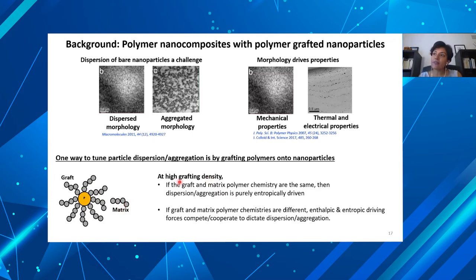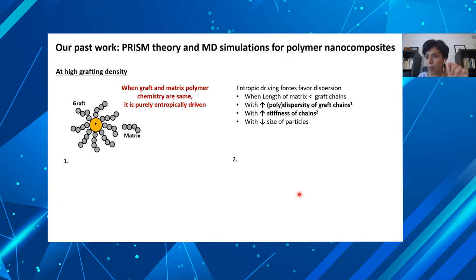So at this high grafting density, if you choose the chemistries to be the same, then essentially, because everything is densely grafted on the particle, the net morphology is driven by entropic driving forces. And of course, if the chemistries were different, then in that case, you're now dialing in enthalpy as well, and how those two chemistries talk to each other plus entropy together dictate whether you're going to get dispersion or aggregation. So I'll be in this second bullet, but I'm going to tell you a little bit about the previous bullet as to the important entropic driving forces, because that doesn't disappear in the second. It's just there along with enthalpy.